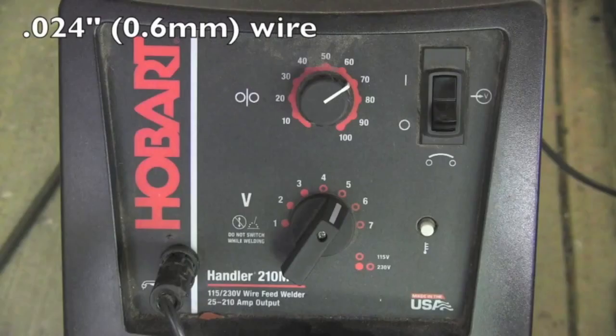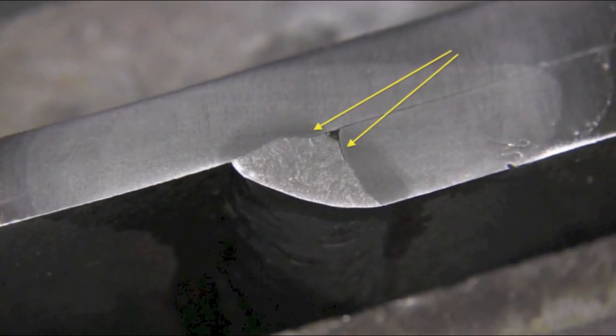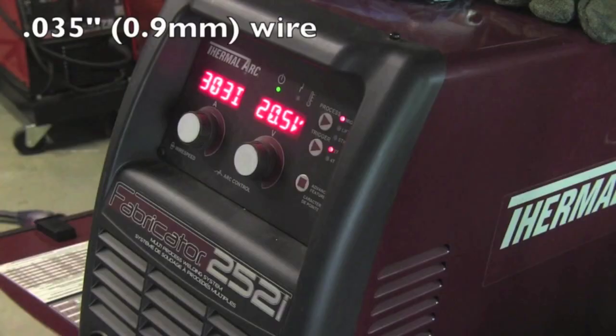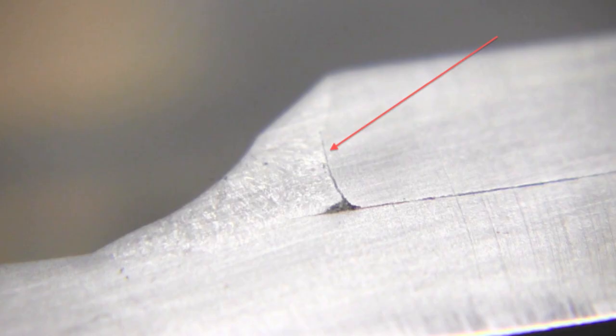All right, like I said, first up here is the small machine with the small wire. You can see the travel speed is quite slow, and you can see it looks a little bit cold, and got a little bit of lack of fusion there in the corner, quite a bit actually. Now the bigger machine, hotter settings, bigger wire, much hotter puddle, but quicker travel speed, and the results on there were actually worse. That hot rolled mill scale proved to be a real culprit. You can even see the rounded edge of that hot rolled mill scale where the molten metal just laid up against it, didn't even melt through it.